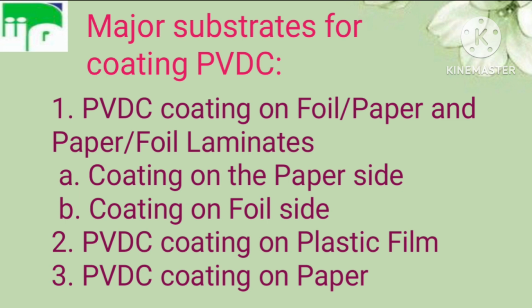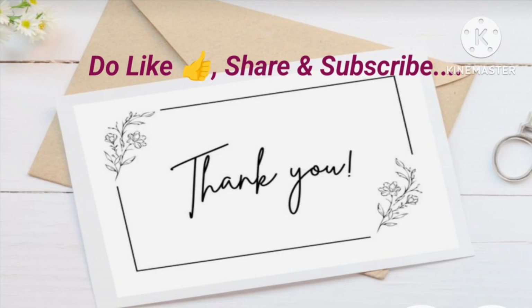For good results, it is recommended to use sized, super calendared, bleached paper. And it has also been observed that the barrier properties of the combination of 2 to 3 thin films of PVDC is superior to that of single coating of PVDC with equivalent total coat weight. Therefore, during the coating, 4 to 8 GSM each of PVDC film is applied in 2 to 3 stages instead of applying a single coating of around 20 GSM. So this is all about PVDC coatings.